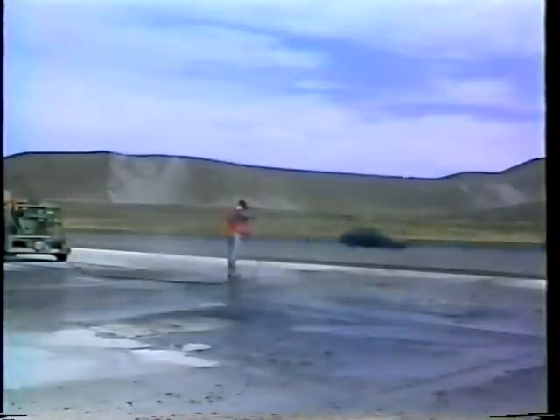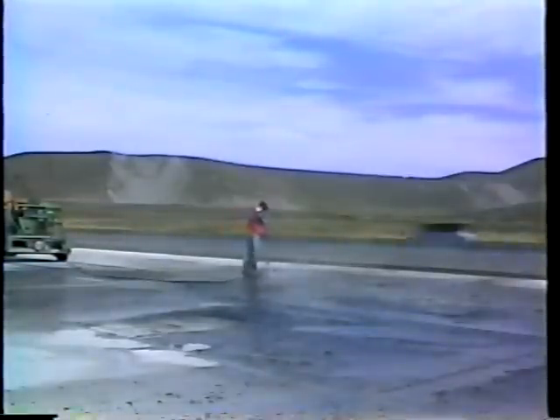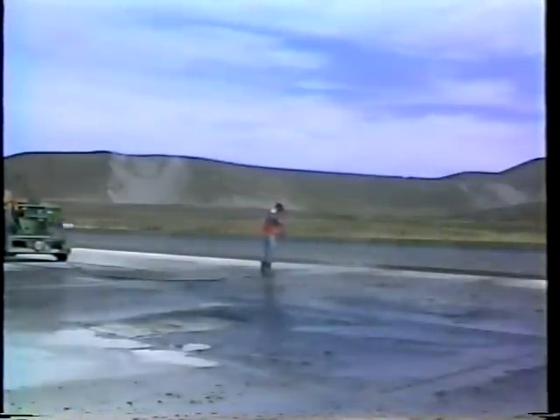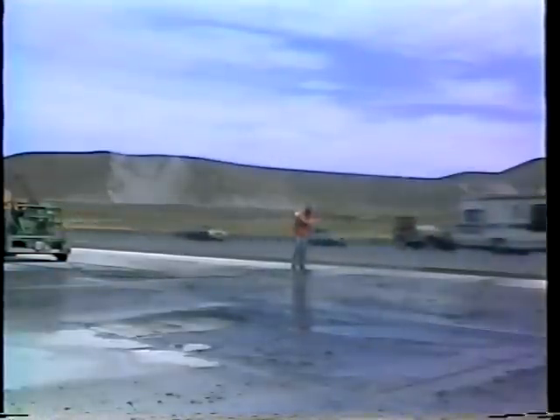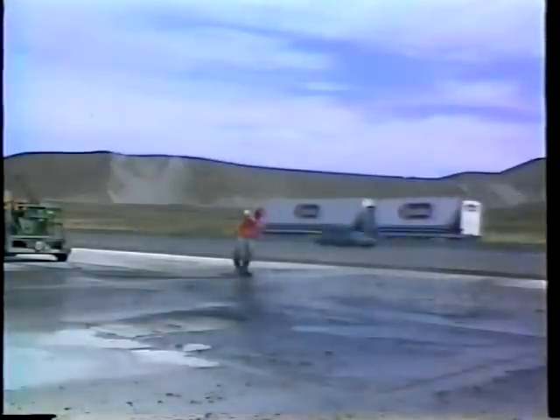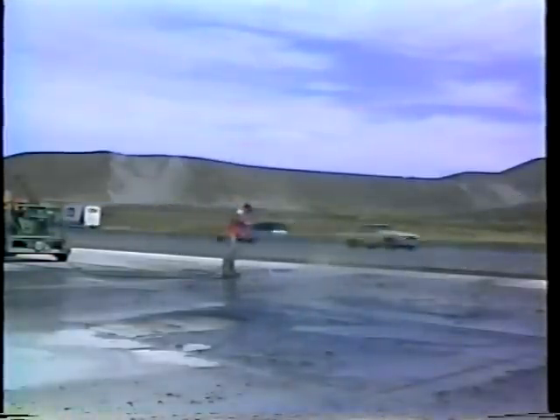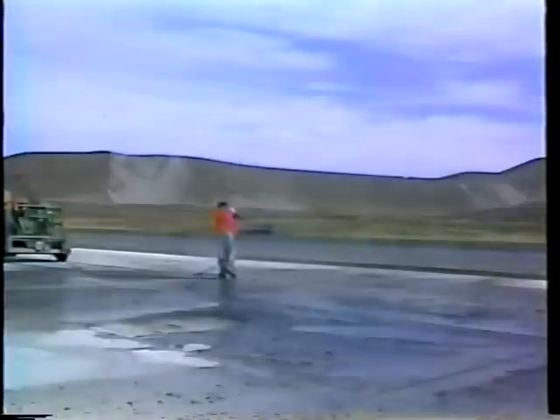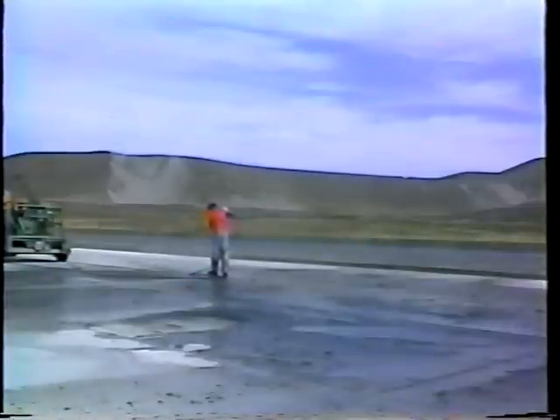The third option is water blasting. Here, water pressures of up to 30,000 PSI are used to remove the deteriorated concrete. This method has two advantages. First, all the material can be removed without the danger of damaging the surrounding concrete. And second, water blasting leaves a clean-cut surface with excellent roughness and angularity, which will promote bonding with the repair material.